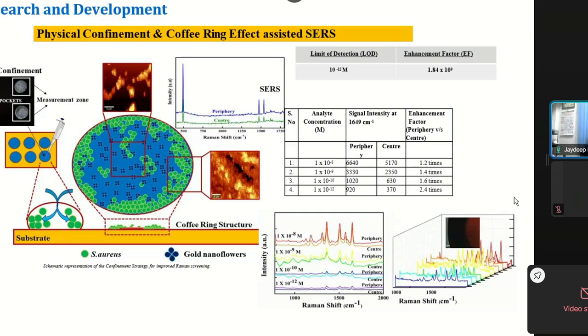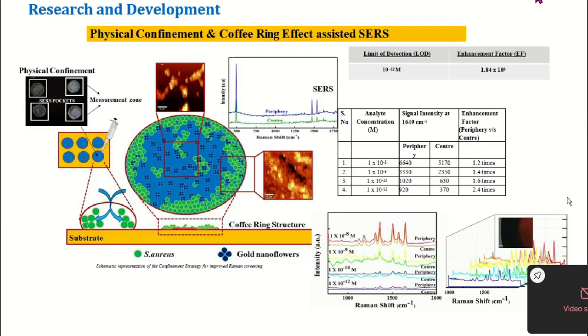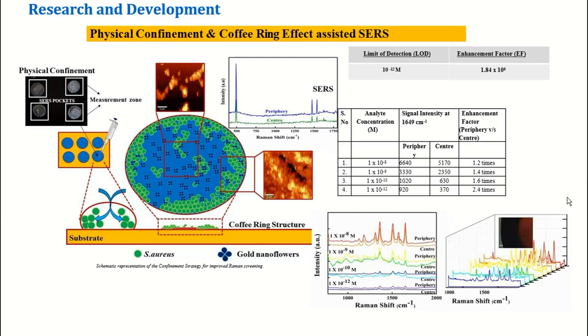But with the advent of nanotechnology, there is a concept called surface enhanced Raman spectroscopy, which has now evolved and taken off, where different nanomaterials can be used as such a substrate. There are two types of enhancement with the use of nanotechnology: one is chemical enhancement, and another is electromagnetic enhancement. With semiconductor, non-plasmonic, basically anisotropic structures, we can do chemical enhancement, and we have shown that we can do chemical enhancement in the range of 10 to the power 4, 10 to the power 5. But with plasmonic nanostructures, we can do the enhancement in the level of 10 to the power 9, 10 to the power 10. And that's why we have now started using this gold nanoflower.